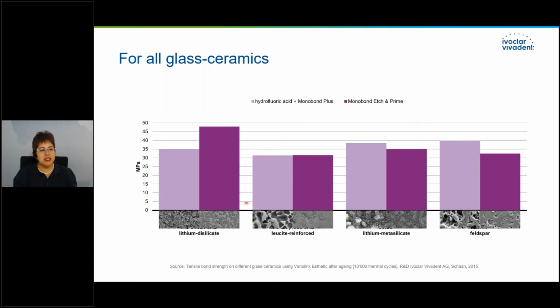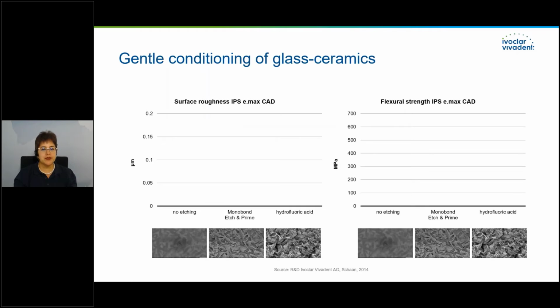The higher reaction here on lithium disilicates depends on the interaction with the crystal phase. The stronger the ceramic, the higher the crystal phase. Therefore, Monobond Etch and Prime has a higher reaction with the crystal phase of this glass ceramic. In general, you can say Monobond Etch and Prime is a very optimized product for the pre-treatment of pure glass ceramic.